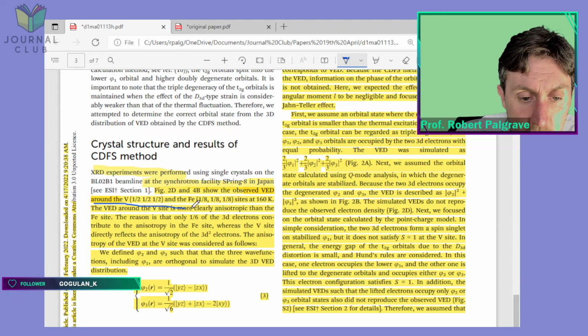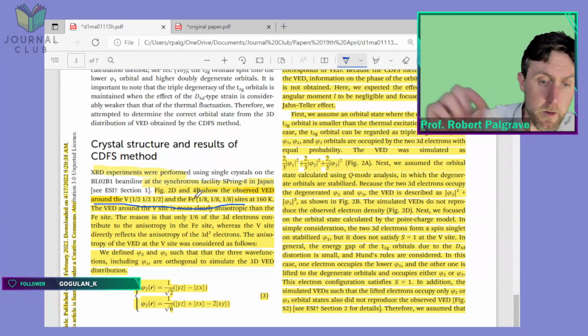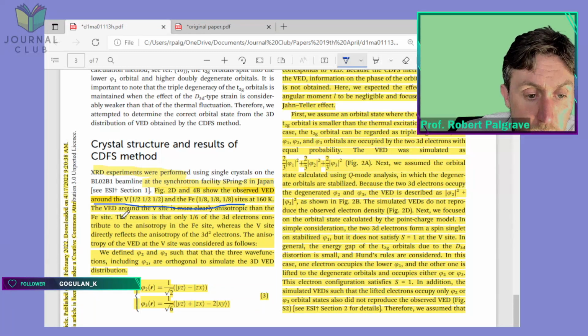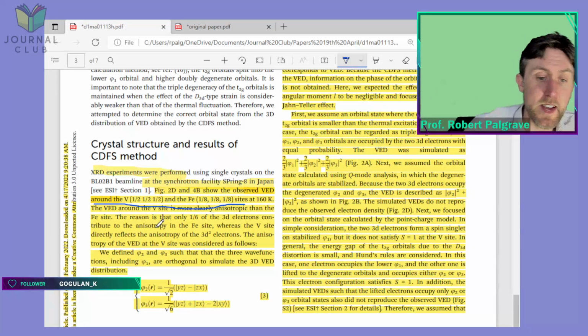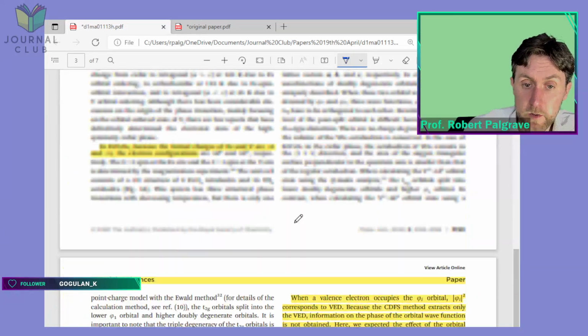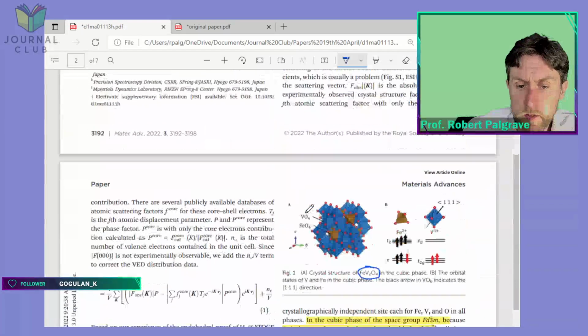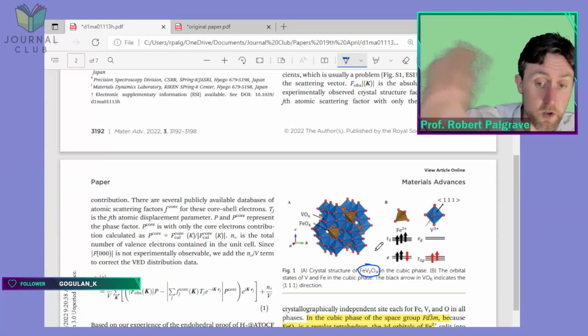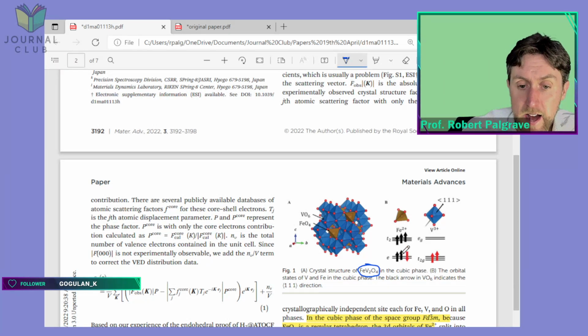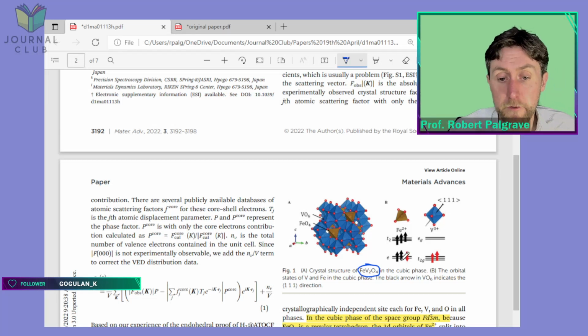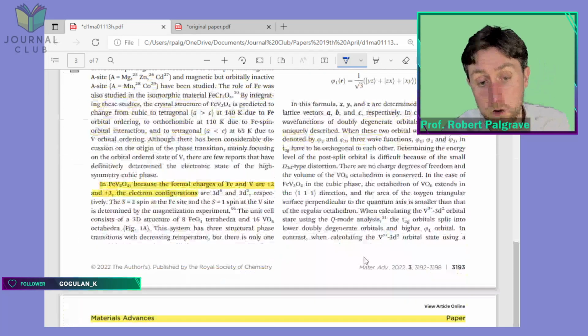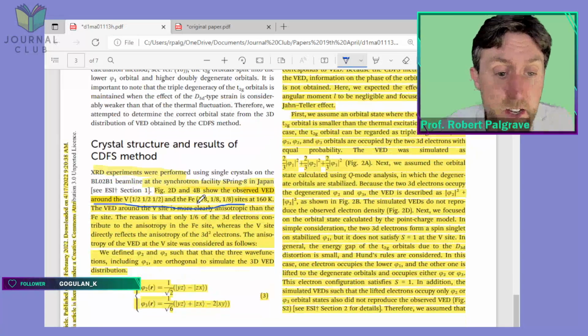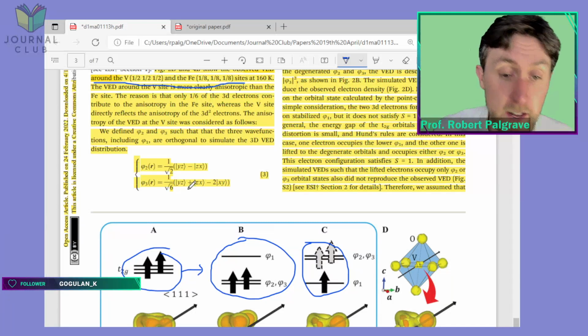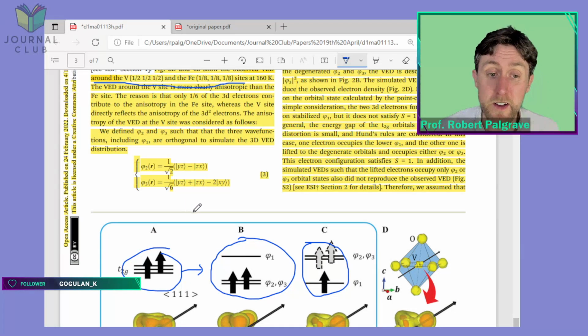Around the vanadium 1/2 position and the iron 1/8 position. That's just particular positions in the unit cell, at 160 Kelvin. The valence electron density around the vanadium site is more clearly anisotropic than the iron site. The reason is only 1/6 of the d electrons in iron contribute to the anisotropy. If you look up here, these electrons are all isotropic, but only one of the 6 electrons has this possibility for anisotropy, with different orbitals that it can occupy. Whereas in the vanadium site, both of the electrons can contribute to the anisotropy. So it's easier to see the anisotropy on the vanadium site, because all of the valence electrons are anisotropic, compared to the iron site where 5/6 of them are not.